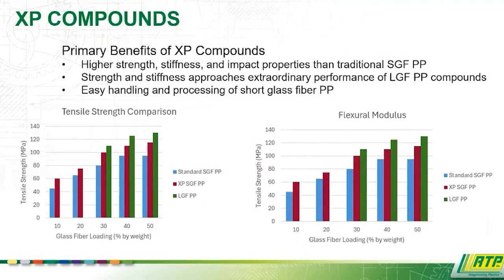XP compounds exceed the performance of traditional short glass fiber polypropylene and even approach the performance of long glass fiber polypropylene in strength and stiffness, as you can see in the graphs, with the standard in blue, the XP in red, and the long glass fiber in green. And this is tensile strength, and this is modulus or stiffness. XP really bridges the gap and approaches that performance of long glass fiber, but it does it in a short pellet, which aids with ease of handling, a bit lower cost, and really just bridges that